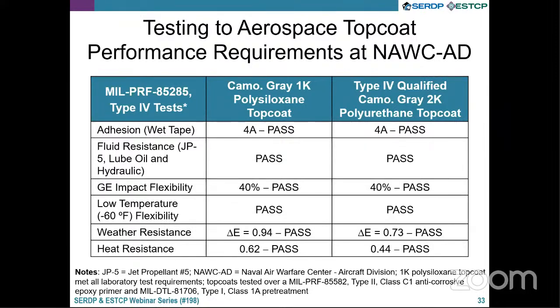This is just a small subset of the tests, basically showing that the camouflage gray single component top coat can pass several of the more difficult tests, similarly to a qualified two-component polyurethane top coat.